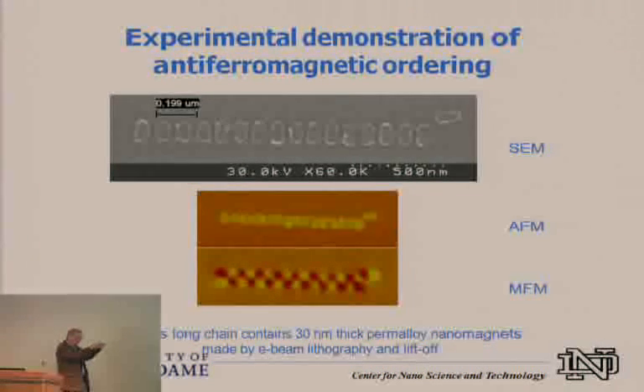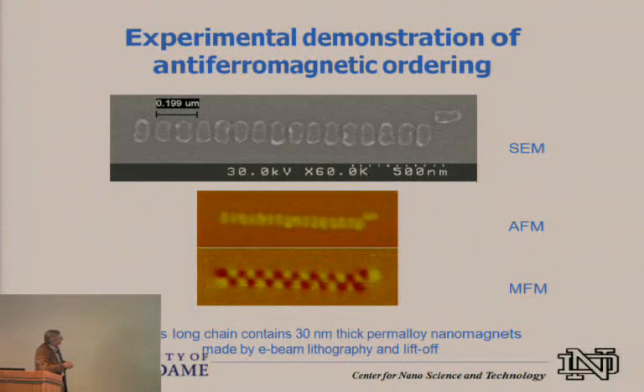Once they point towards the hard axis, then a small magnetic field, which could be a fringing field from the neighbor, or it could be a fringing field from the input, pushes it into the correct state. And so within a scheme like that, we can also use horizontal dots as shown here, where the easy axis is along the lines of the clocking field.